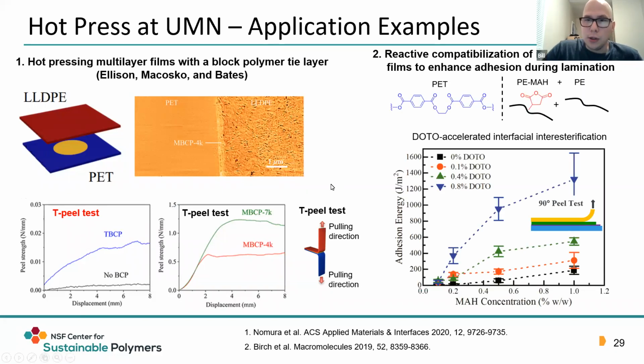Additionally, looking at reactive compatibilization, the diffusion of the two phases causes the reactive groups on each polymer to interact, and then you get adhesion as well without the need to include a third phase, such as the block copolymers previously. So it's a kind of an in situ method to compatibilize two incompatible materials.